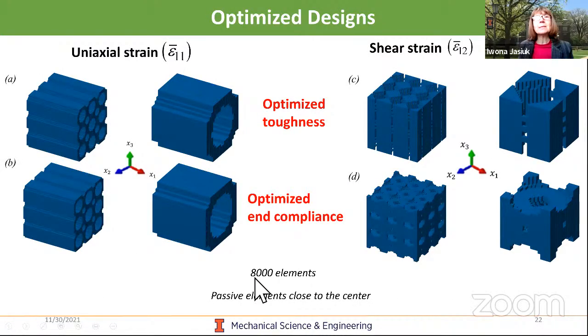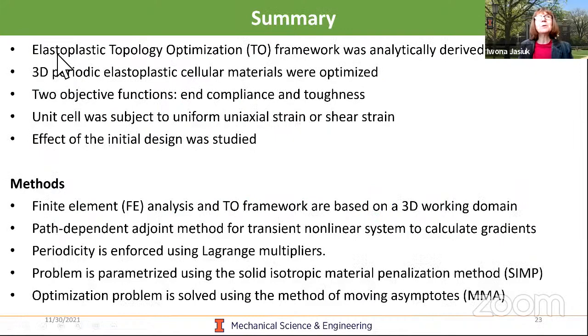For the optimized design, we used 8,000 elements, for the uniaxial case, where the uniaxial compressive strain is applied horizontally. Optimized toughness gave this final design for the initial design used, and the optimized compliance approach gave this configuration. So these are tubular structures. And then for shear strain, similarly, tubular structures were obtained.